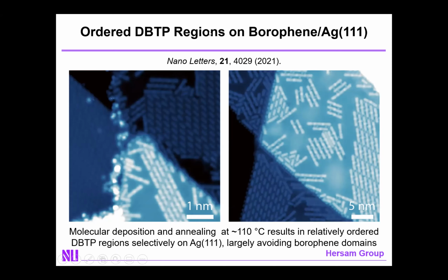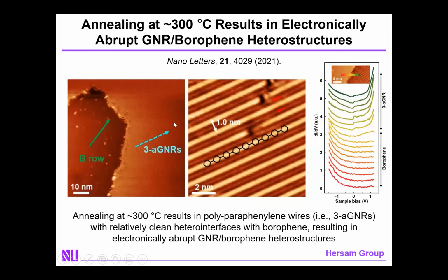If you heat this up now to 300 degrees C, those molecular precursors now assemble into graphene nanoribbons. In this case, we get so-called 3-armchair graphene nanoribbons, also known as polyparaphenylene wires. These are semiconducting structures, and you can see that clearly in the electronic density of states. And you'll note that they form a very sharp heterointerface with borophene.